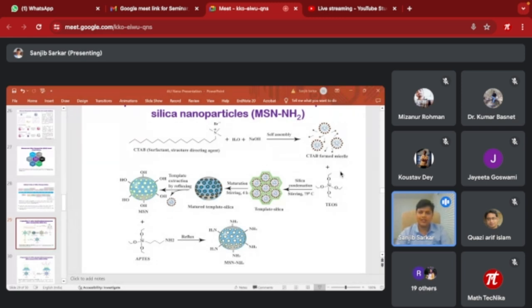So we also did a histological study. We found that in diabetic mice, you can see some abnormalities in the muscle, thinning of the muscle fibers, and in the liver tissue there are also some abnormalities, which were recovered when you use silica nanoparticle with vitamin K.